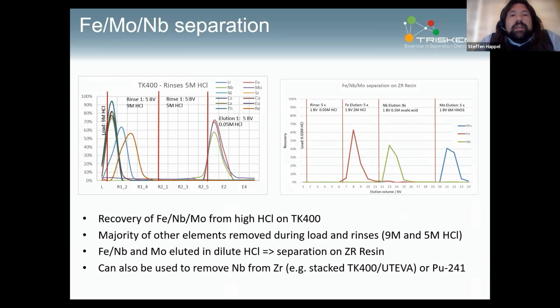So if you load from 9 molar HCl, pretty much the majority of matrix elements and of beta emitters wash through the resin. Pretty much anything else is eluted in 5 molar HCl. Then you can recover the iron, niobium, and the molybdenum as a group in dilute HCl, directly load onto ZR resin. That's a hydroxamate-based resin, and then separate step by step: iron that you obtain as a 2 molar HCl solution, niobium as an oxalic acid solution, and then molybdenum as a 6 molar nitric acid solution. So that's something that's currently being tested in the frame of this cooperation.